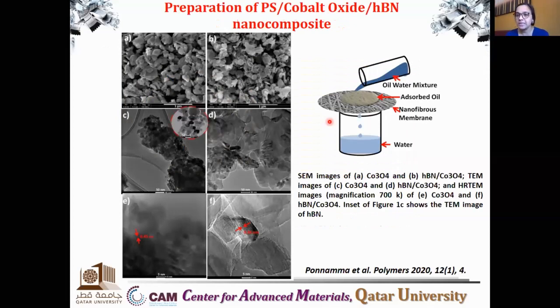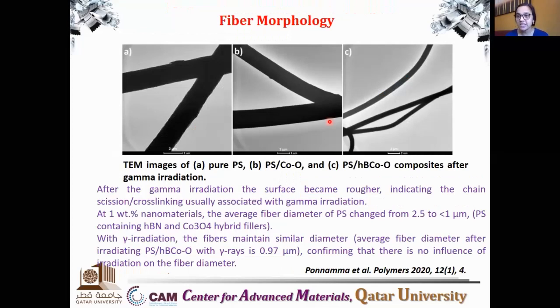And continuing with this, we also synthesized some polystyrene materials based on cobalt oxide and hexagonal boron nitride. Hexagonal boron nitride is just similar to the graphene structure. And we made a hybrid nanocomposite by combining hexagonal boron nitride and cobalt oxide. We synthesized this hybrid material in our lab, and we mixed it with the polystyrene. Again, the same process was adopted, electrospinning, and here also we got nice electrospun fibers, and we did the gamma radiation, in the same line as the polystyrene carbon nanotube research. After the gamma irradiation, the surface became rougher, and a high crosslink density was achieved, so that we could ensure good filler polymer compatibility, or filler polymer crosslinking density.